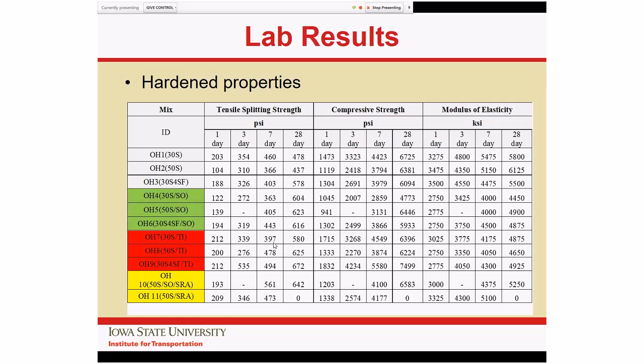I was out there when they did the crack survey and saw exactly what Peter reported here, that you really couldn't find any on the internally cured deck. So I'm pretty happy with that. Just as a side note, there's been a lot of research on the early age cracking of the decks. And Peter, correct me if I'm wrong, but from what I remember in the literature reviews, if you can control your early age cracking within the first 3 years of the bridge deck, you're really setting up that baseline for the curve moving forward, which I believe was taken into account in your life cycle cost analysis, Peter. Correct. Yeah. Okay. In fact, no, the life cycle did not include the effect of cracking.